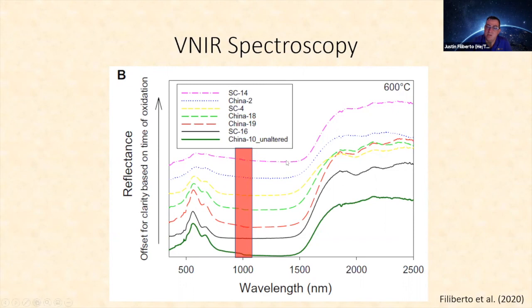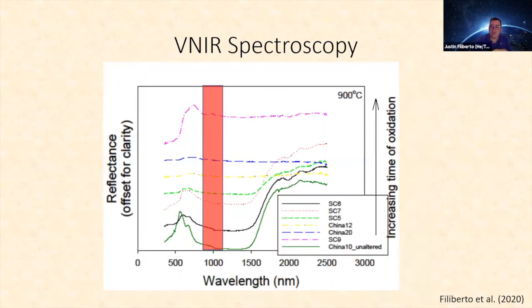This is more or less a flat line telling us we wouldn't be able to tell that this is olivine, whereas this is nicely beautiful olivine. Going to 900, again, these are offset for oxidation. We've got a beautiful olivine. And after a month at 900 degrees, this is a beautiful and perfect hematite spectra.